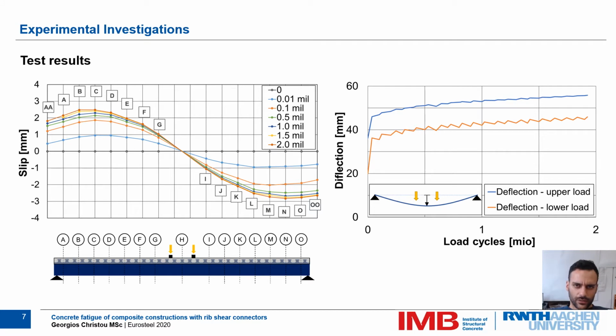If we now take a look at the results, we can see on the left side of the slide the slip in several sections of the girder for several timeframes between 0 and 2.0 million load cycles. As expected, the slip increases over the lifespan of the test. The slip increase ratio is very high in the first 100,000 load cycles, and after that, the ratio of the slip increase declines constantly. After approximately 1.5 million load cycles, the slip increase is almost negligible.